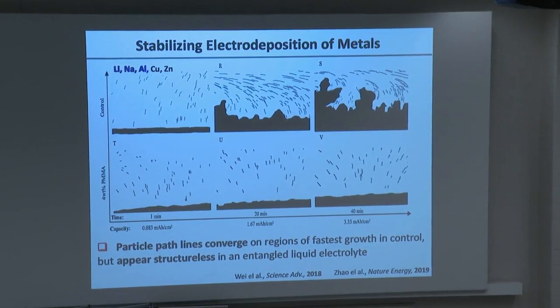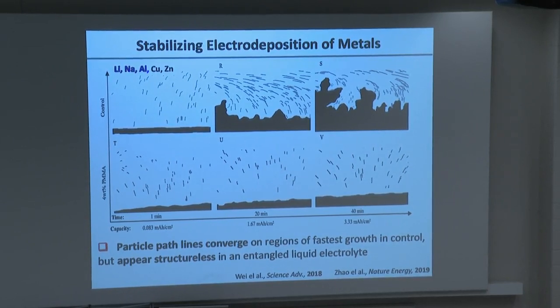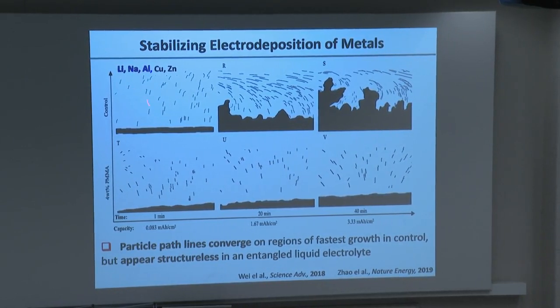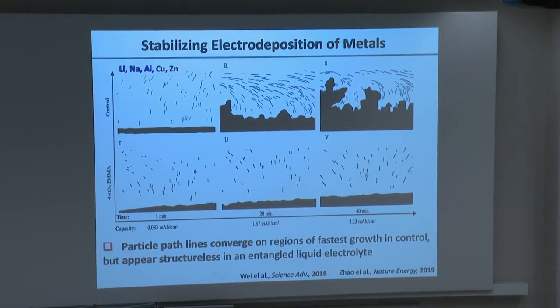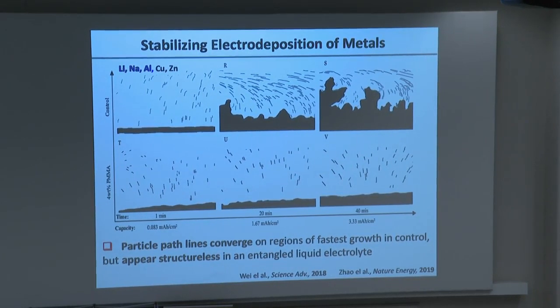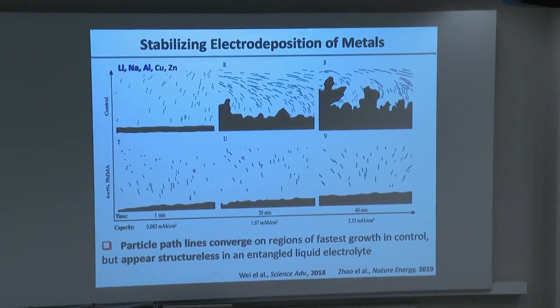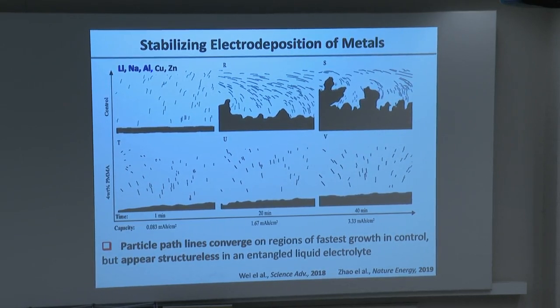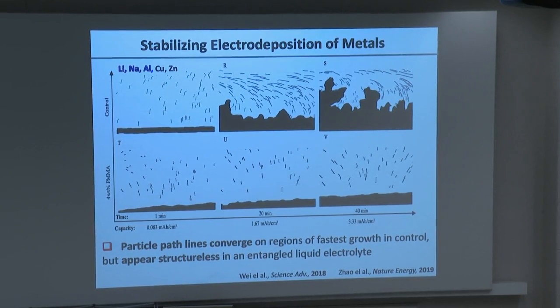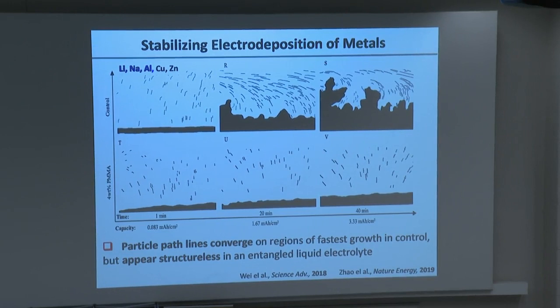Now, I said the student was special, that she was really surprised by this result, even though we predicted it. And so she decided to do it for sodium, aluminum, copper, pretty much anything she could get her hands on. And as reported in this paper, it works in every case, indicating that this phenomenon is really not about the chemistry of the metal. It's more fundamental and more physical, and it is an indication that by stopping the hydrodynamic instability, we can stop this so-called morphological growth that produces dendritic deposition. So that was fun.